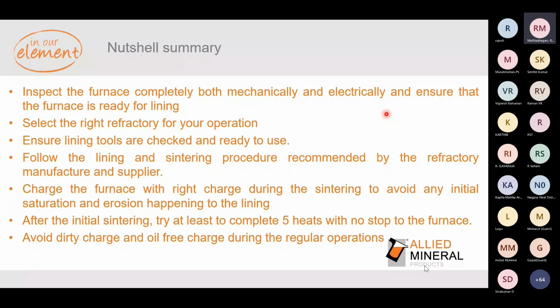And again, in case the furnace is going to be put into a lot of thermal cycling, then fused silica is one of the solutions which you can look into. And there are a lot of grades in fused silica also, ranging from 15% to 40%. So depending upon your cost viability, we can choose fused silica. That comes under selection of right refractories for your operation. Ensure lining tools are checked and ready to use. Follow the lining and sintering procedure recommended by the refractory manufacturer and supplier.